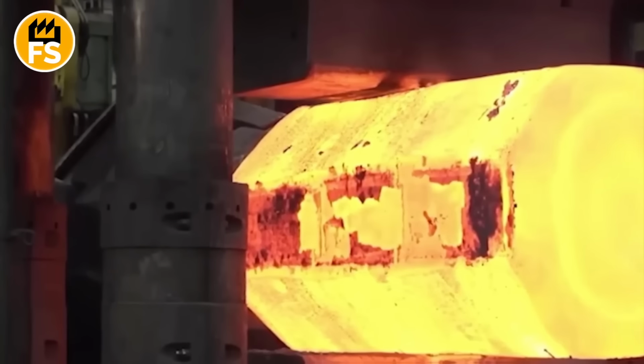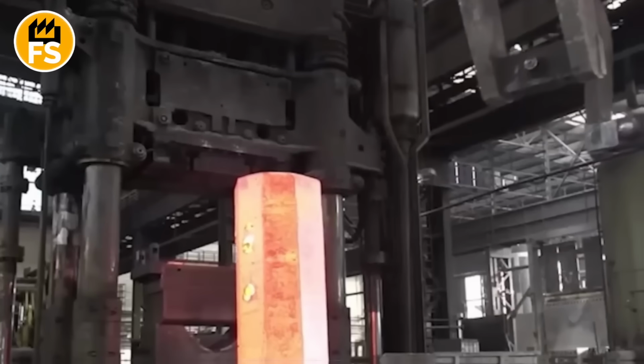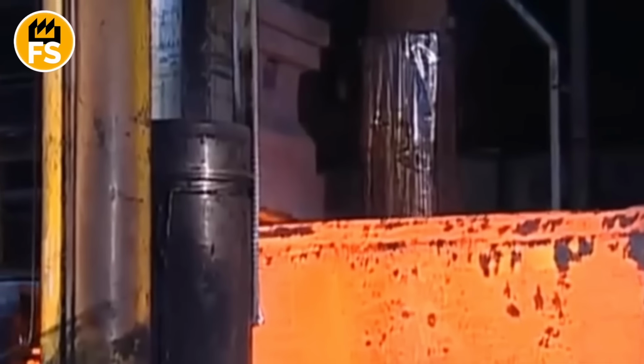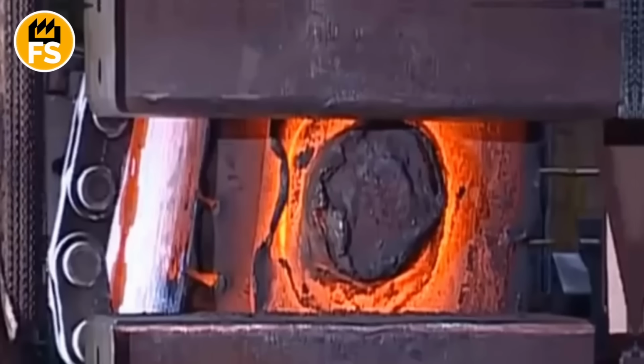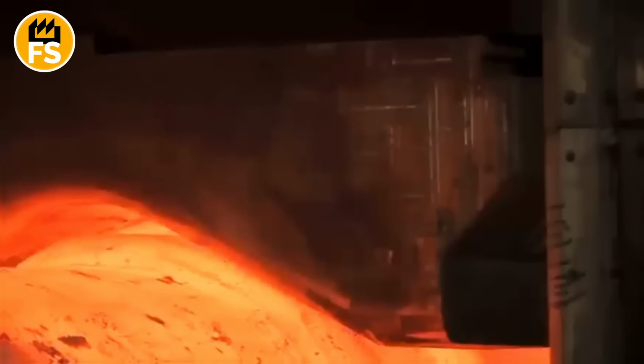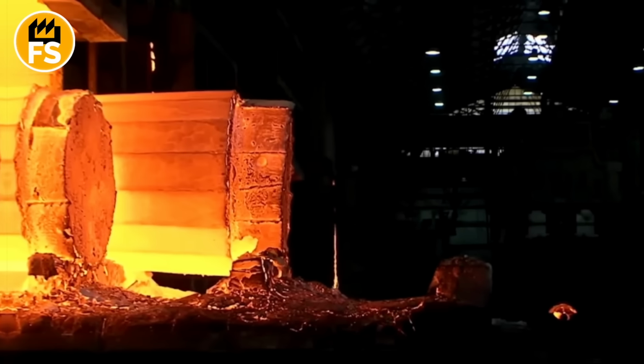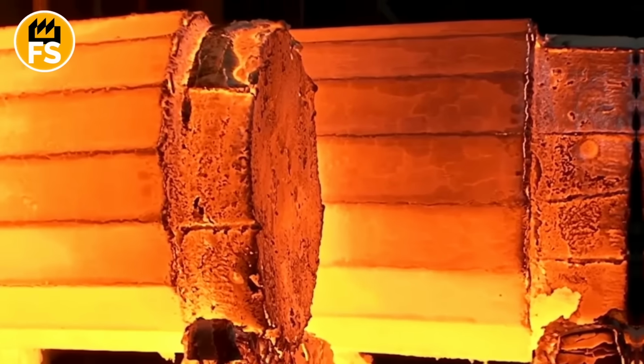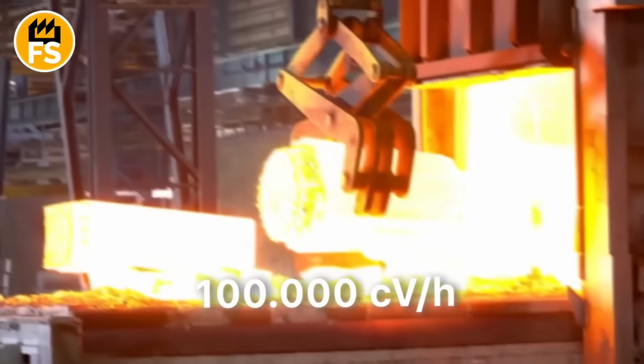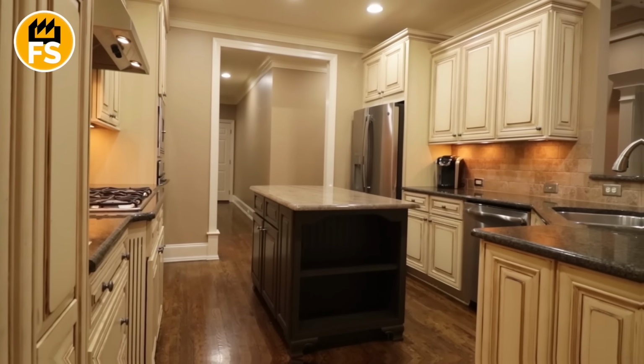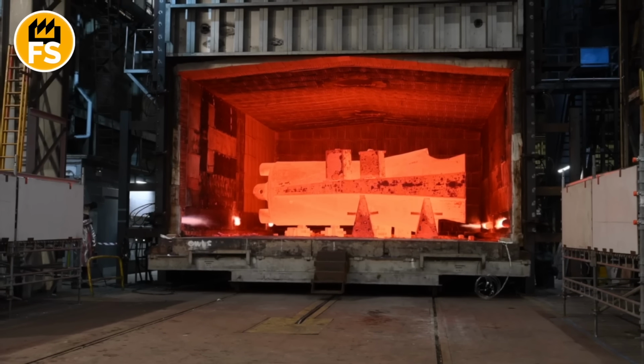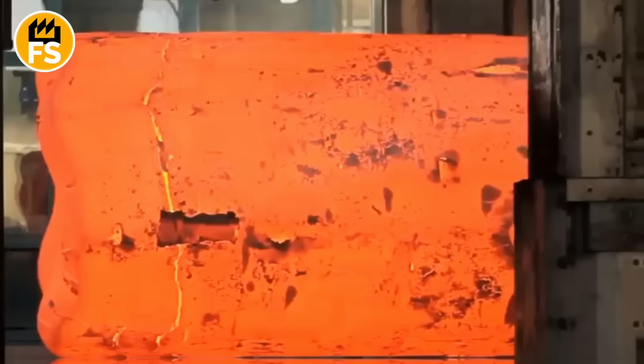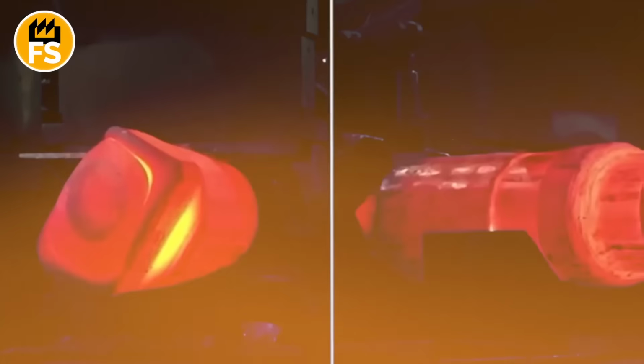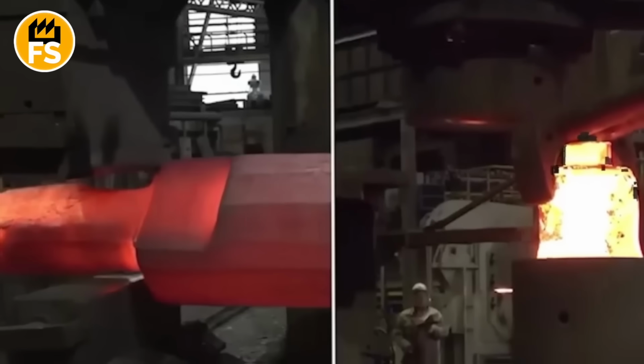The forging process for such an ingot takes several months. It's a constant cycle of heating, pressing, rotating, and reheating. Each press stroke is a precise calculation aimed at achieving the required internal geometry and mechanical properties. The energy needed to maintain the furnace for heat treating ingots during a 2-week cycle can exceed 100,000 kilowatt hours. That's comparable to the annual electricity consumption of dozens of typical households. During heat treatment, the allowable temperature deviation in the furnace throughout the entire volume can be only 40 degrees, which requires the use of high-precision multi-zone control systems.